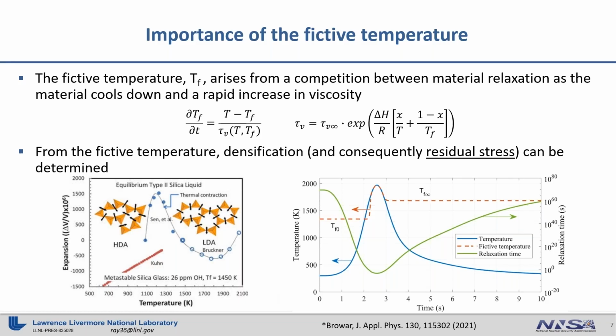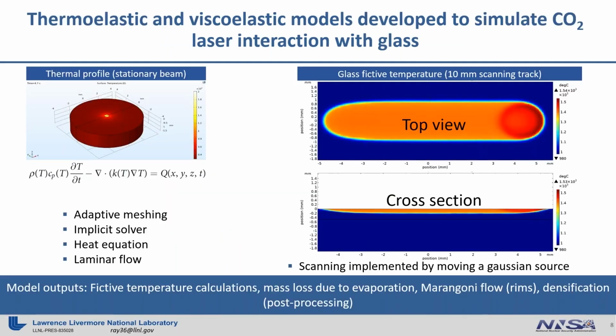Then you can get from that the polishing depth. And if you have densification, then you might have some areas that are locally densified, and then some areas where there's no densification. So then it stands to reason that there's going to be residual stress. So there's a lot of things that come from being able to predict what the fictive temperature is going to look like. So thermoelastic and viscoelastic models were developed to simulate the CO2 interaction of glass.